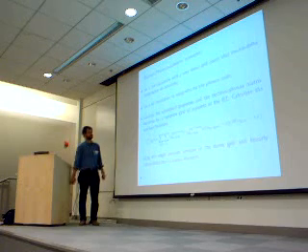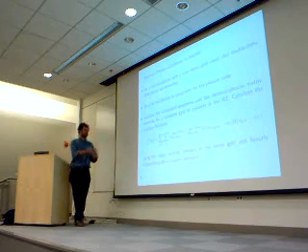And whenever you need this product of matrix elements, you interpolate linearly. So this G you only have on the coarser grid, and when you need them for the denser grid, you linearly interpolate them on this denser grid.